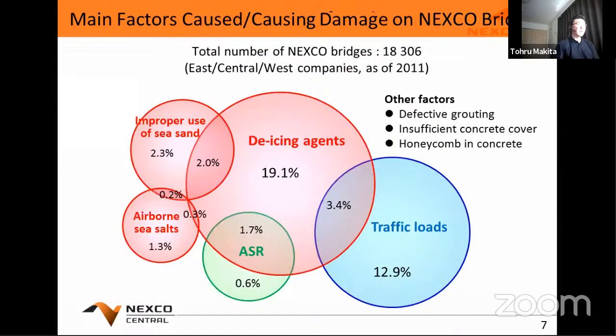So these are the top five factors causing damage on NEXCO bridges. The most detrimental is the de-icing agent. And the second is the truck load. The truck load caused fatigue damage on bridge decks. And sea sand was extensively used without removing the chlorides in the 1960s and 70s, mainly in the western part of Japan. The other factors are defective grouting, insufficient concrete cover, and honeycomb in concrete.